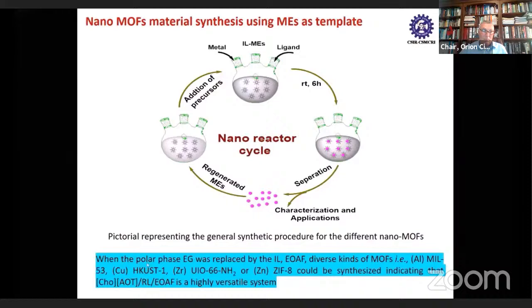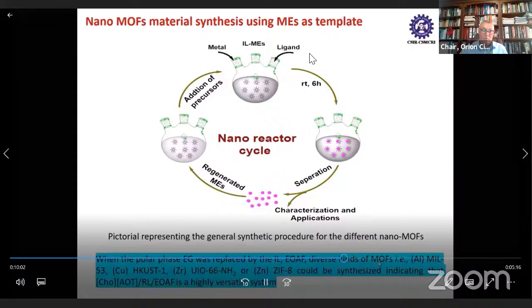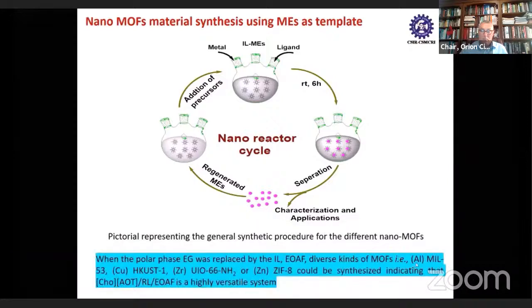nanomaterials. And to our wonder, when we replaced ethylene glycol in the medium with an ionic liquid, we could synthesize different kinds of metal organic framework with a single microemulsion system. We synthesized aluminium-based MOF, zirconium-based MOF, zinc-based. So all kinds of MOFs could be synthesized in an ionic liquid-based microemulsion system.